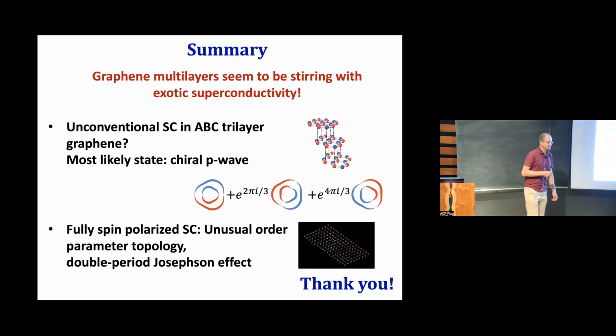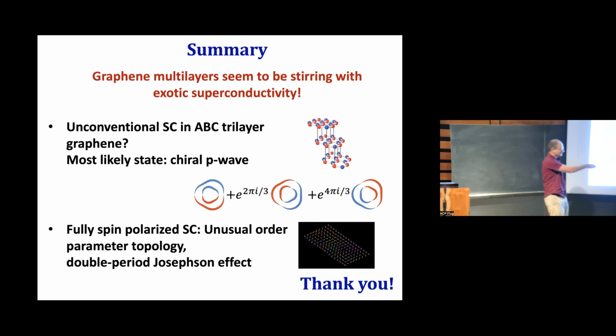Yeah, so I think it's not clear. The question is whether the nearby ferromagnetism is actually playing any role in superconductivity other than just competing with superconductivity. Clearly, when you go deep into the ferromagnetism, it kills the superconductor. This is a calculation I've actually done with Zaletel's group. We considered what we believe is the nearby generalized ferromagnet and looked at fluctuations of that. And it turns out it leads to exactly the same state, to our surprise. So you're saying if it was a spin-only ferromagnet, it wouldn't give you that? Not this, no.